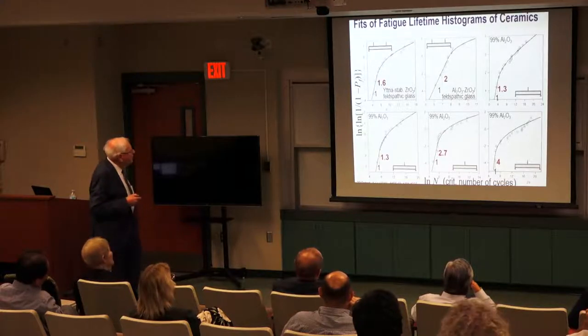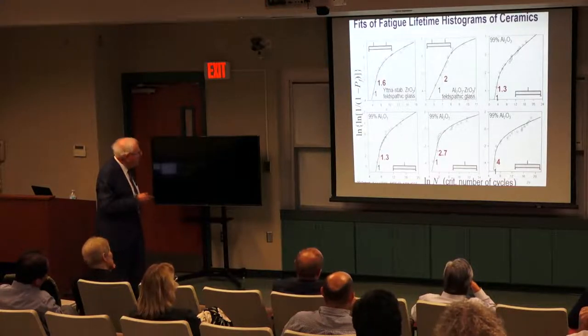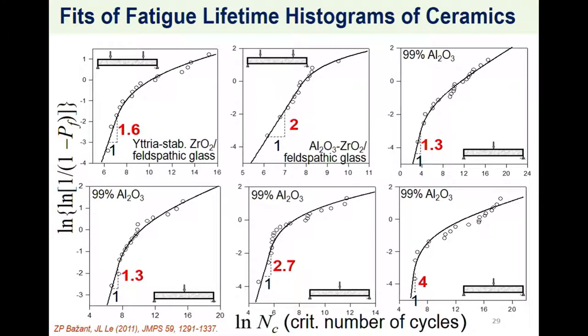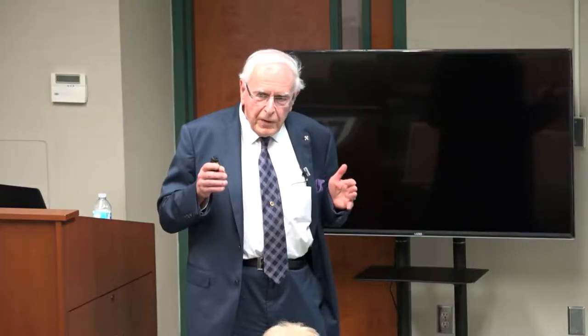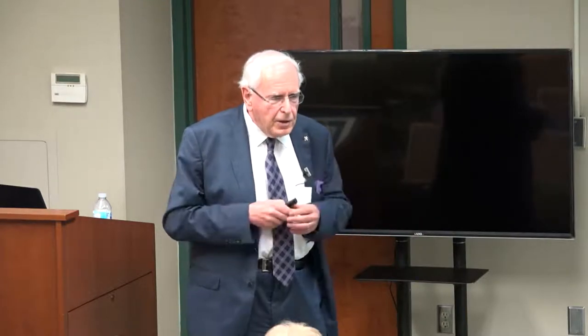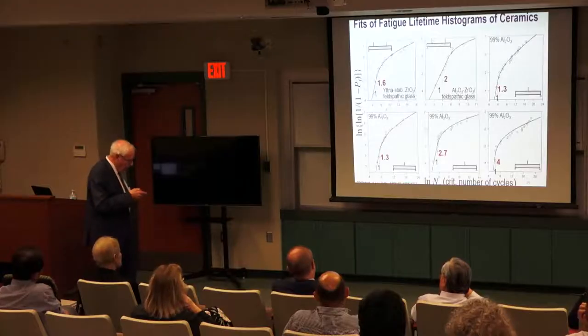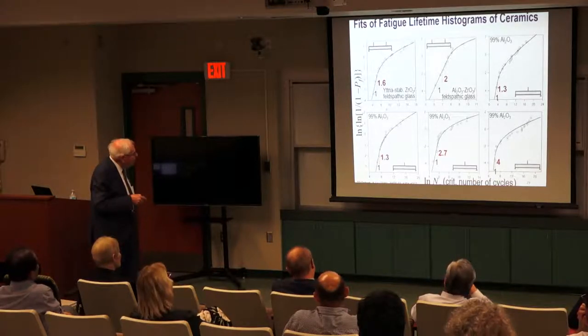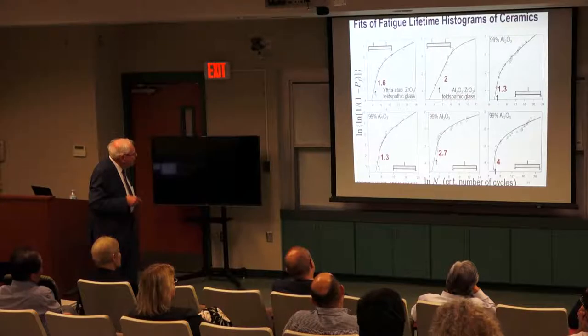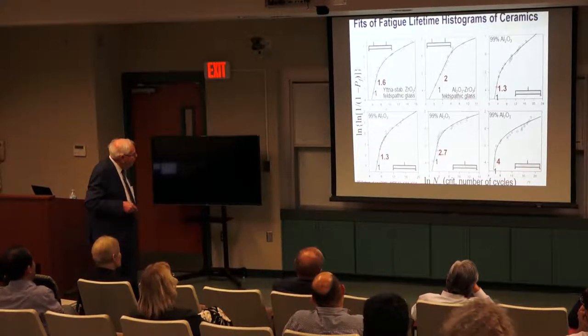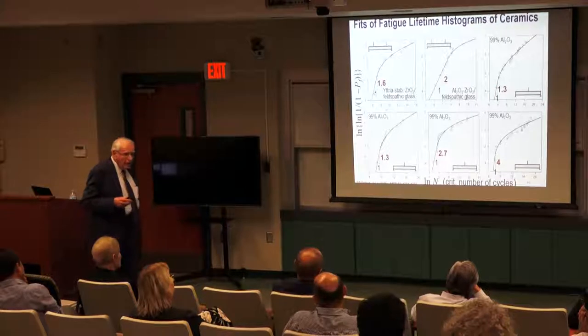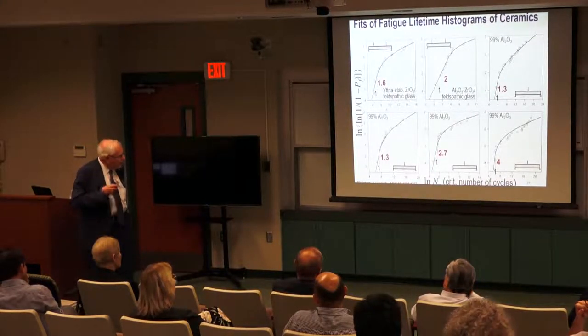So these are fatigue lifetime histograms for ceramics of various materials. You see, for lifetime, same behavior. If the structures are perfectly brittle, lifetime will be Weibull, so it will be a straight line in this scale. Why? Because again, the structure fails where the first element fails, right? So it's like weakest-link statistics. But what is observed in quasi-brittle materials are these transitions which you can fit exactly. You see that the exponent now is not 40, it's very small, and that means for lifetime the size effect is extremely large.